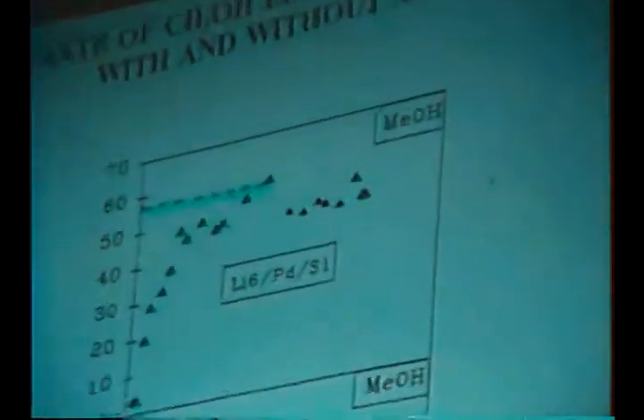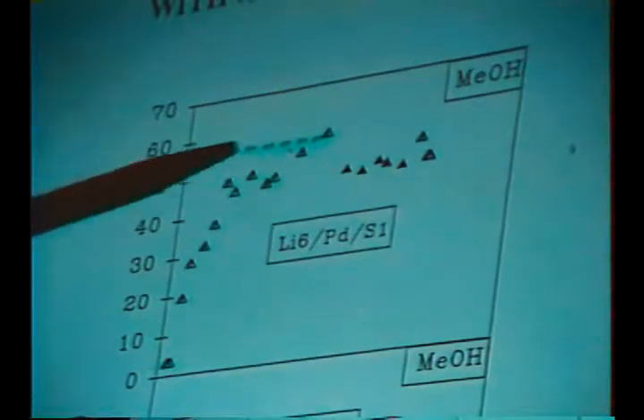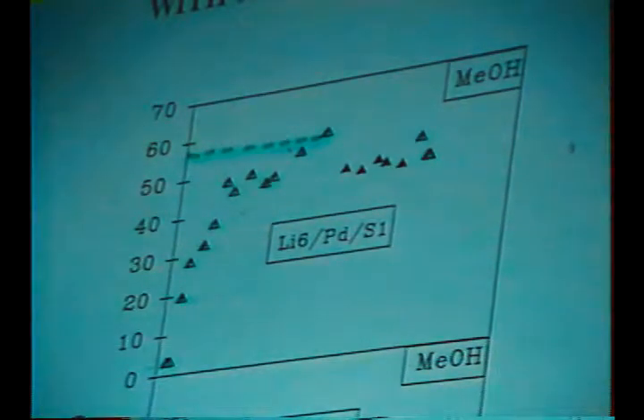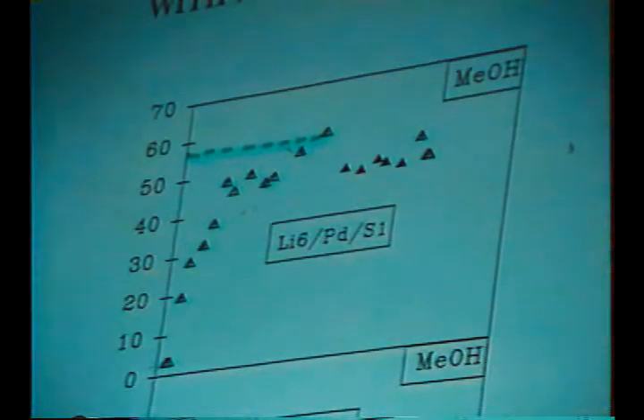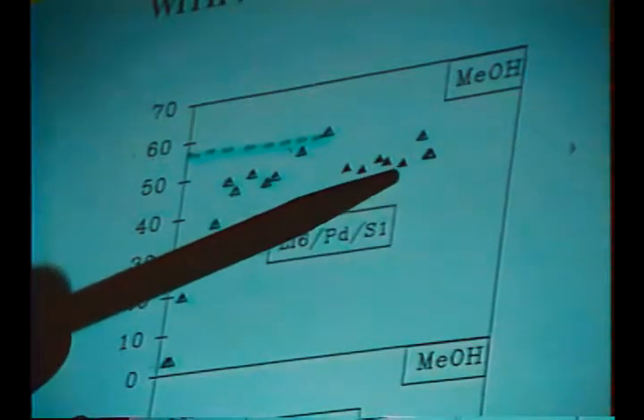Can a composite catalyst do it? The first thing I want to show you is some results from the dual bed experiments. We have a bed of palladium catalyst followed by a bed of a zeolite, 10 to 1. The top graph here is simply the lithium-palladium silica catalyst, 6 to 1 lithium-palladium ratio. Here is roughly the average activity after we reach steady state. The closed circles is when we add isobutylene, the open circles in the absence of isobutylene. You see that addition of isobutylene reduces the activity, but it stays fairly constant.